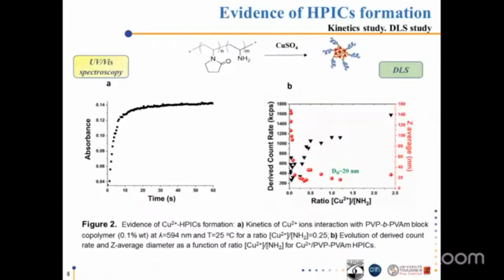To obtain the kinetics of copper loading at molar ratio 1 to 4 between copper ions and polymer, we followed the evolution of maximum absorbance as a function of time directly after the addition of copper sulfate to polymer solution. The obtained kinetic graph, presented in figure 2a, shows very fast complex formation, which is completed within 5 seconds. The HPICs formation was also proved by dynamic light scattering, figure 2b.